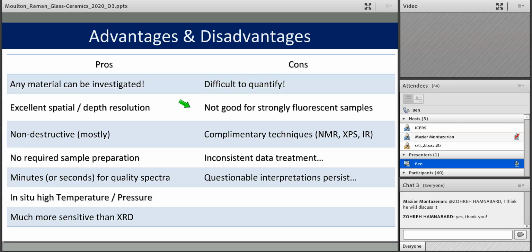It's not good for fluorescence samples. So if you have manganese, for example, where there's a lot of electronic transitions in the visible range, it fluoresces very strongly, and you won't see any of the vibrational modes. Usually, in a good study, it's best to have two different techniques, whether it's Raman plus NMR, XPS, or infrared, to get a consistent picture of your system.